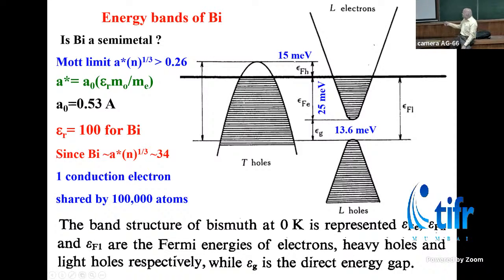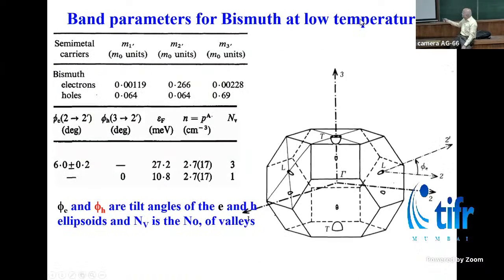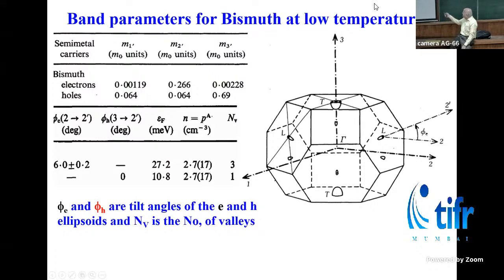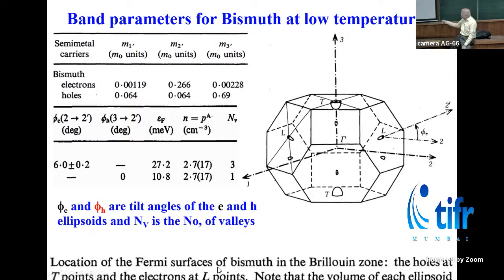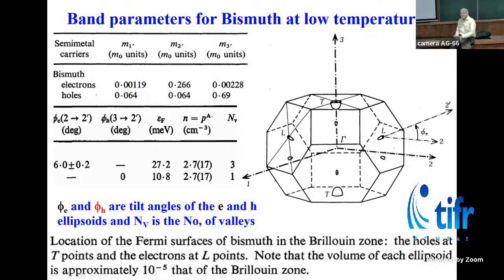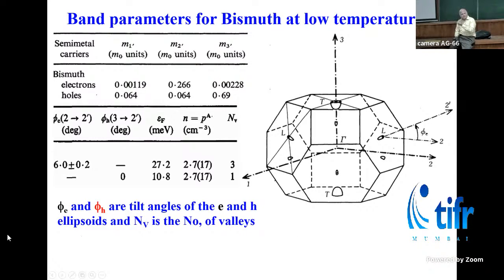It has 3 electron pockets, tiny electron pockets, and 1 hole pocket. And those small areas of the Fermi surface are what is responsible for the electronic properties of bismuth. And what I'm going to tell you is that it goes superconducting at 0.5 millikelvin.